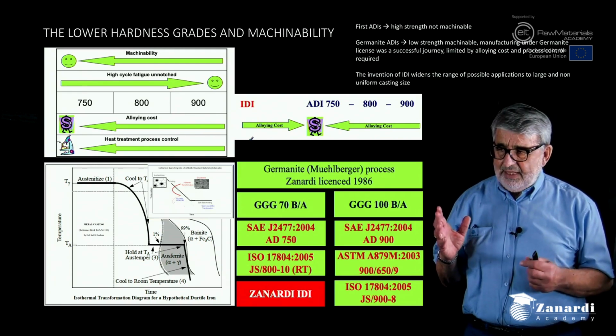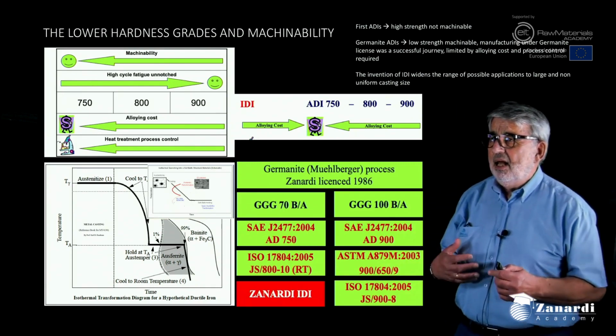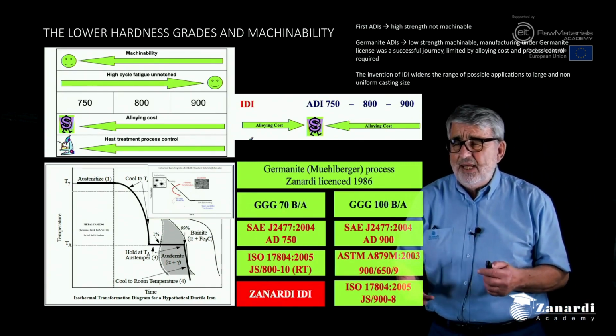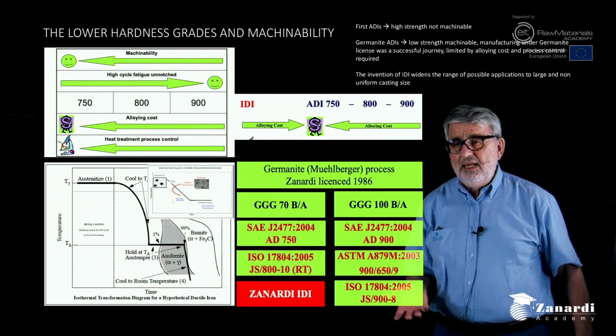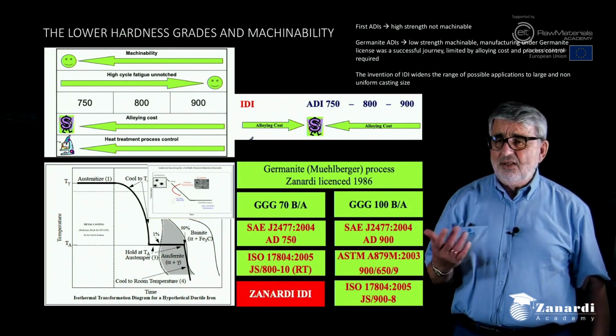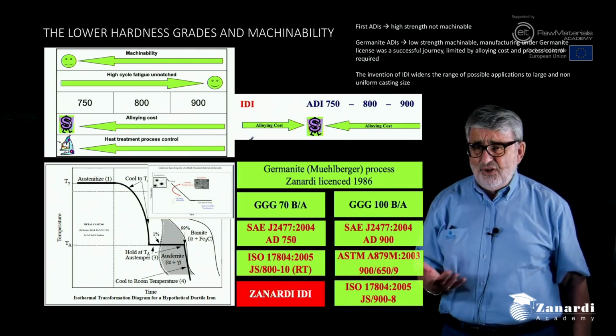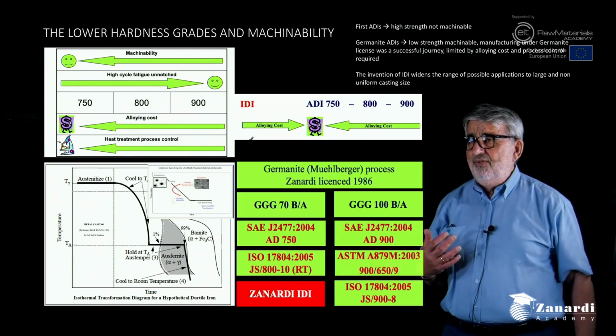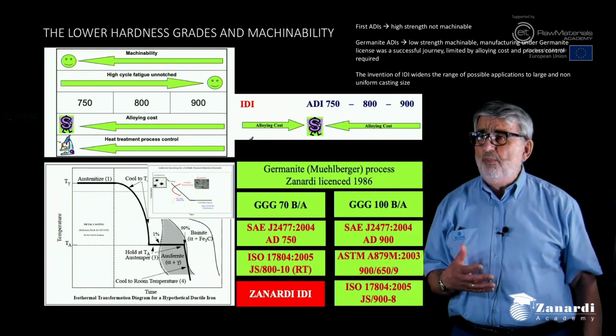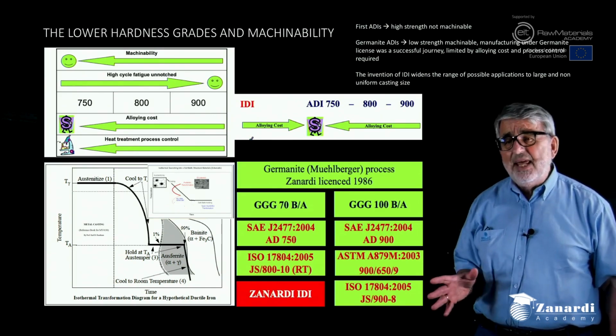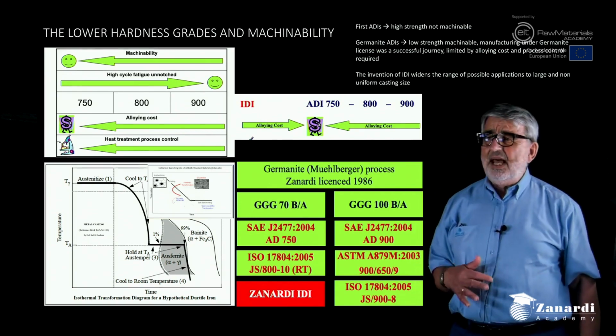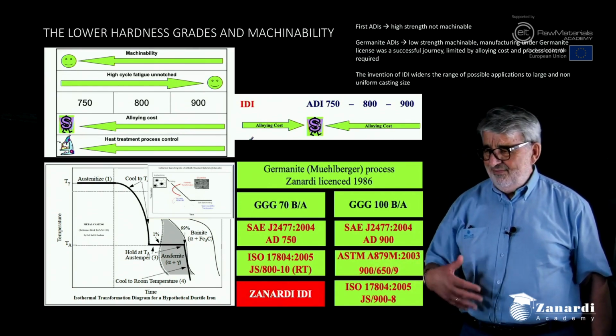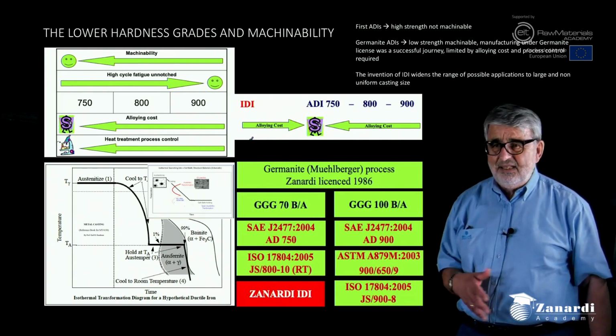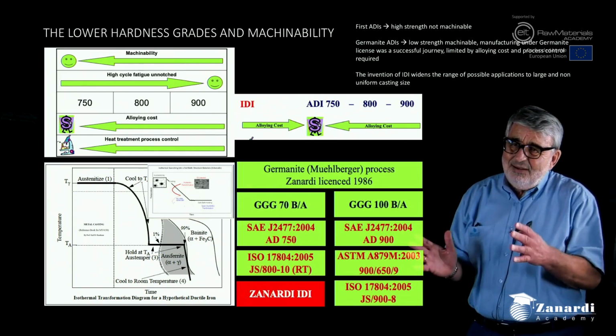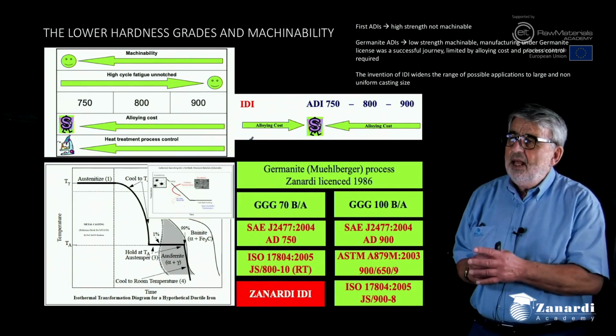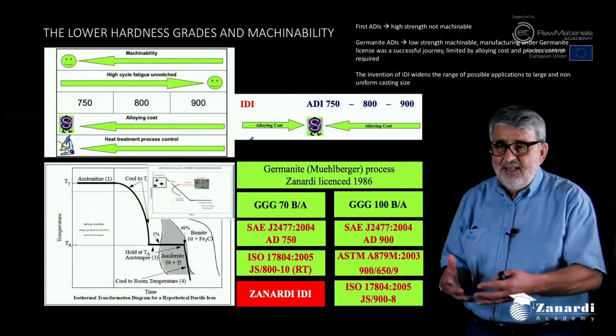For this, the low grades process has been invented by Dr. Muehlberger in the 70s with a patent called Germanite that was licensed firstly for the lowest grades to the Foundry Katrineholm in Sweden of SKF Group for producing axle bearings for high-speed trains. And then in 85 it was licensed, after 3 years of studies and tests, to Zanardi Fonderie. And so at that time started the so-called machinable ADI that was dedicated to the low grades 750, 800, 900.